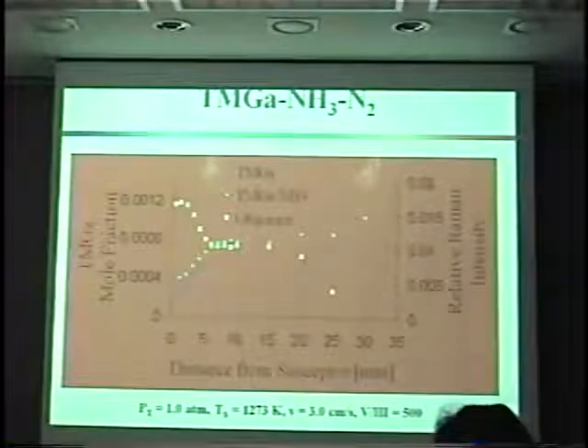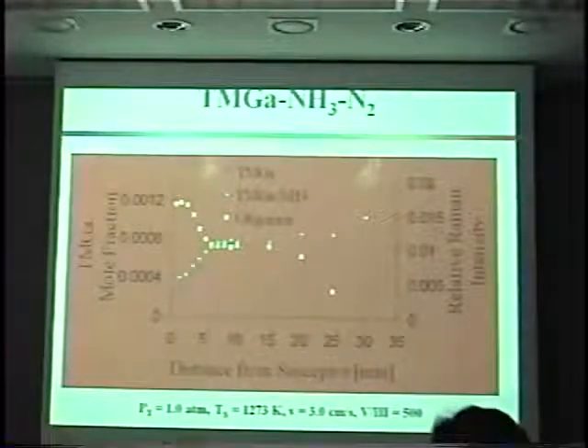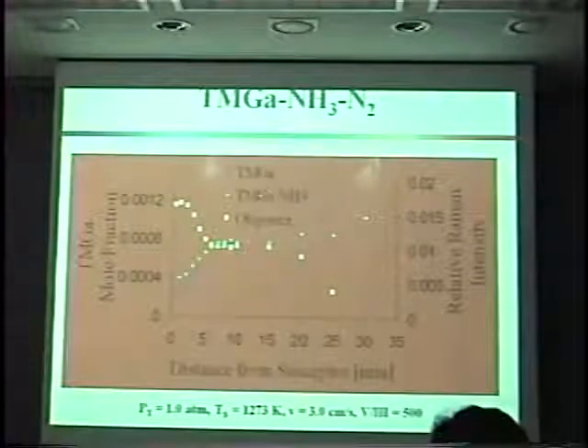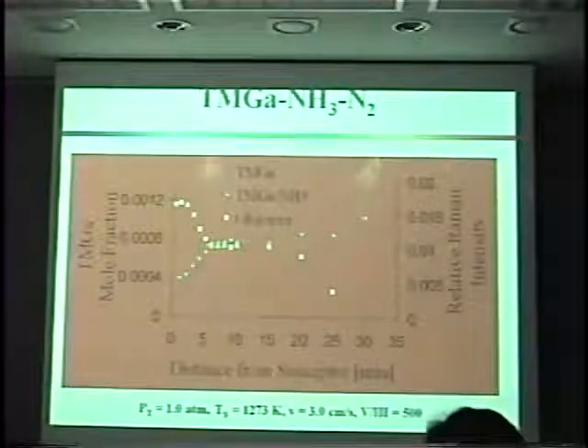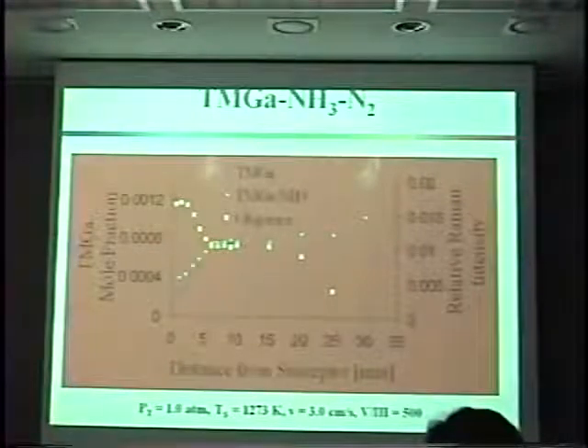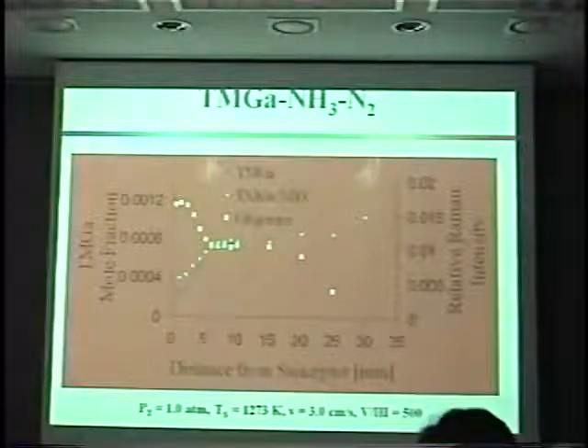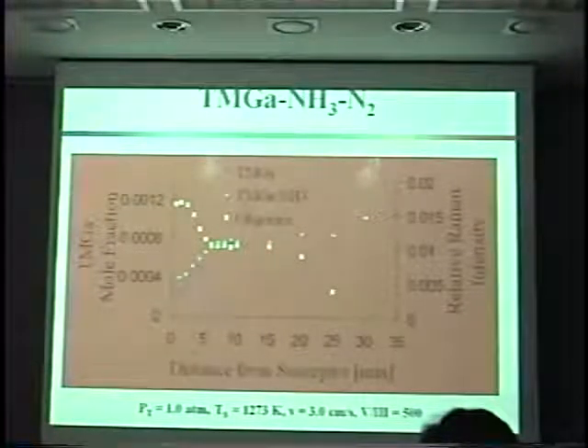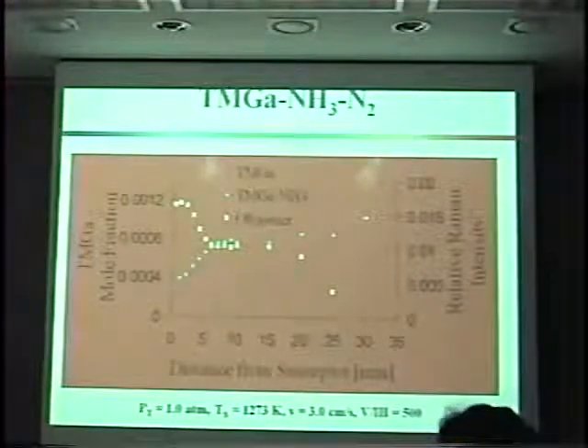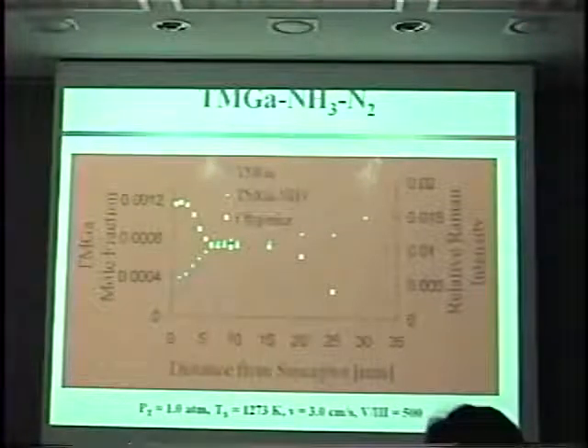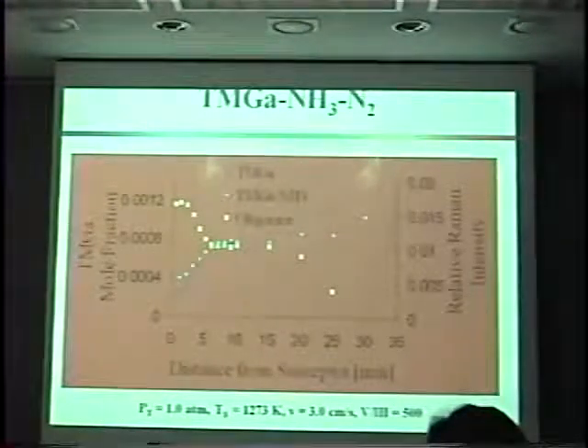Once we get to the hot zone, we then have the release of trimethyl gallium from the adduct. It starts to disappear, and as a result of the trimethyl gallium being present, with the adduct we get additional oligomer formed. Now that we know the kinetics, now we have rate constants, we've gone back and done the reactor design problem. What temperature, what flow rates, what kind of reactor design do you need to be able to preserve the gallium in the adduct formation and deliver the most gallium and ammonia to the surface for subsequent reaction. So I think that's a good example of chemical engineering working. Step through to the last.